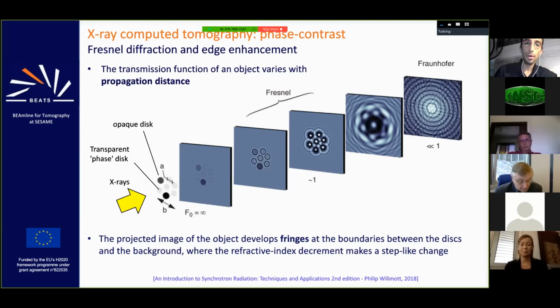When the propagation distance between the sample and the detector is 0 or very short, you see that only the imaginary part of the refractive index gives the contrast. So we have only the 2 opaque disks leaving a significant image on the detector. On the other extreme, when you go too far from the detector, you have Fraunhofer diffraction patterns, and this is what is used, for example, in X-ray diffraction or small angle scattering.